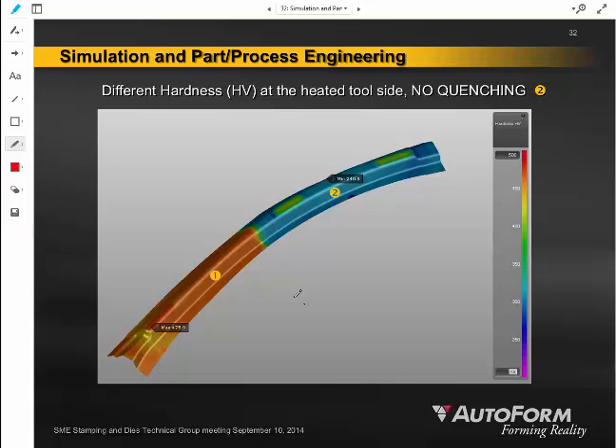And you can see we also will not only measure and try to predict that microstructure, but also show what is the hardness of the material, right? The strength of the material is being measured in terms of Vickers hardness. What is the strength of the material in these areas? And again, where I see this orange coloring, those are materials that, because of their martensite purity, their martensite content, are very high in the hardness scale. And these areas where I had my pads were a little bit lower in the overall hardness scale, but still significantly harder and stronger than the areas next to them, which are in these blue or aquamarine shades.